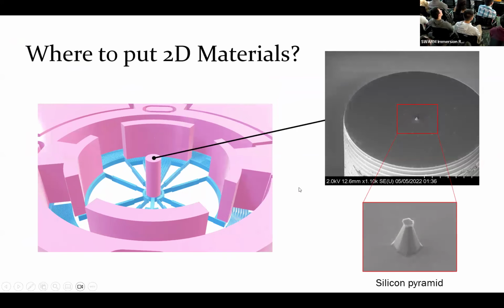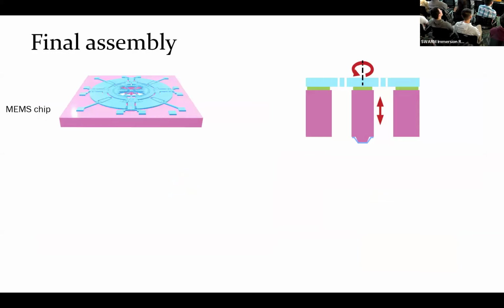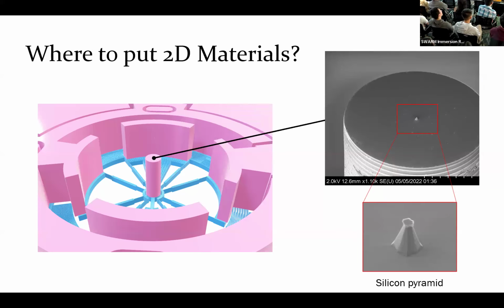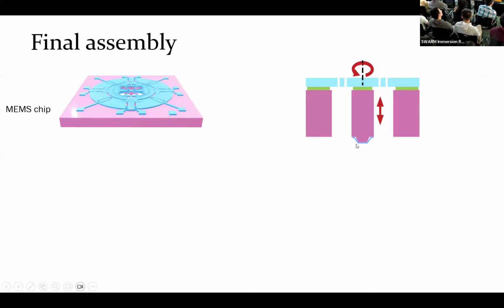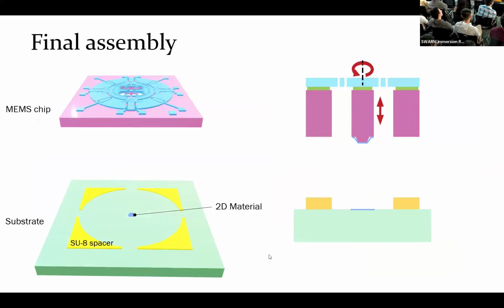So now where do we put down the 2D materials? On the back side of the device, we have fabricated a protrusion in the shape of a pyramid just by anisotropic silicon etching. And now what we can do is tent a 2D material just like on a pyramid. So you can put down a 2D material just on this tip, and it will look approximately like that. So you have a piece of 2D material on the tip on this MEMS device. And I have another 2D material on a substrate, and this substrate can be any material, but we're making it with